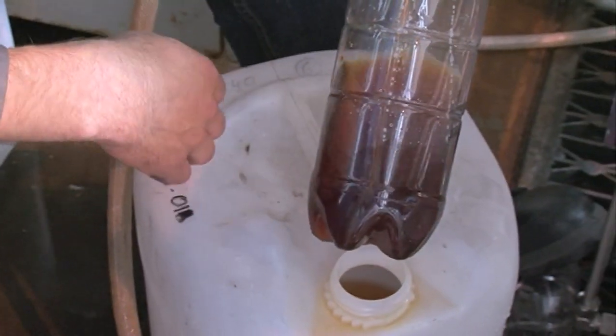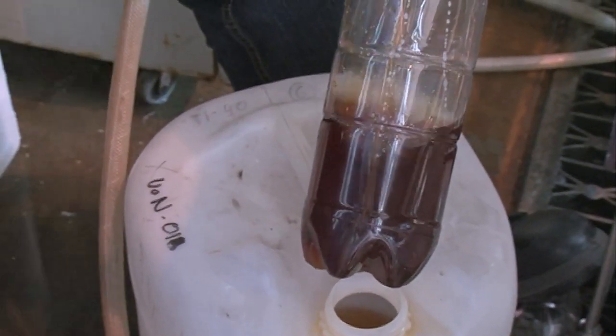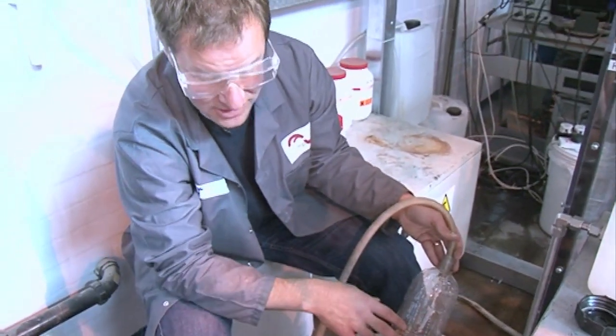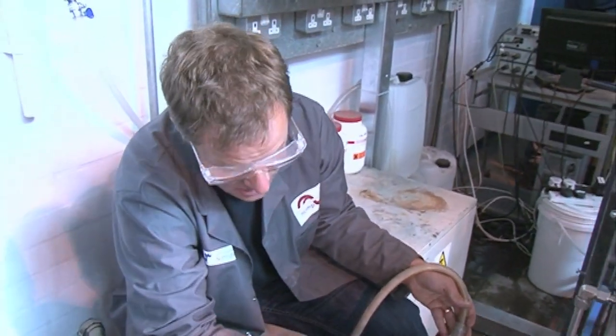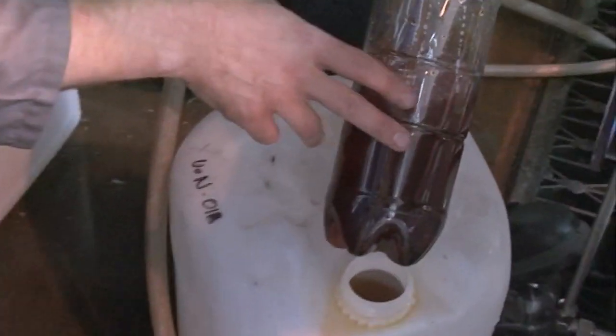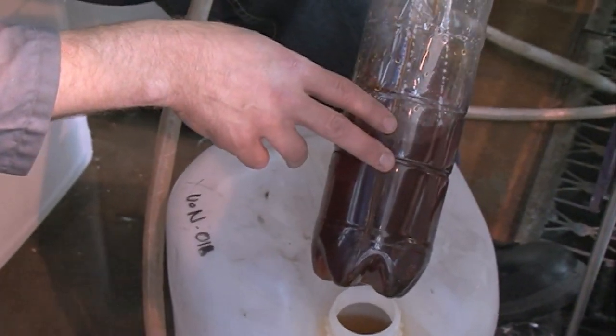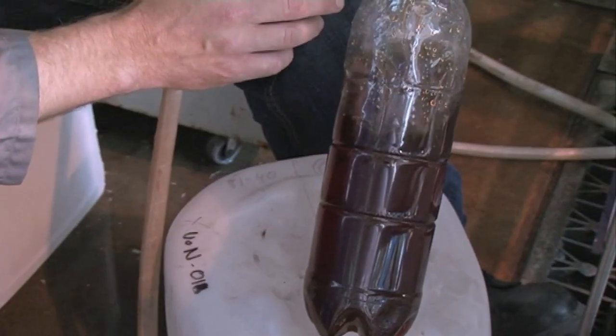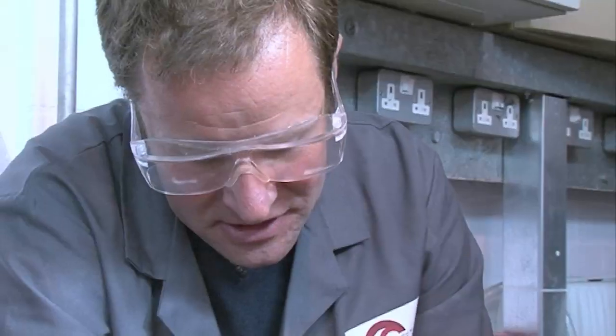You can see it's a red solution. What went in before was orange — so if it's not working, because we're diluting it down, you just get a really light orange. But you can see this is coming out dark red, and that means we've got five nanometer iron oxide particles. We always run with haematite to start with, just for tradition, because it's got a good colour and we know it's working.